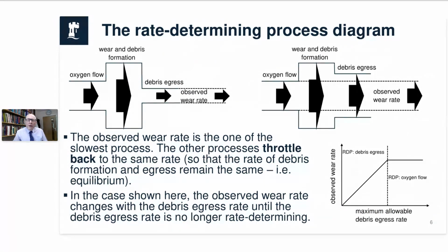the debris loss from the contact. And we say that the wear rate that we observe in this case doesn't really matter what the wear and debris formation is. If that changes a little bit, it's not going to change anything because everything's controlled by the debris egress in this sort of area. Likewise with the oxygen flow.